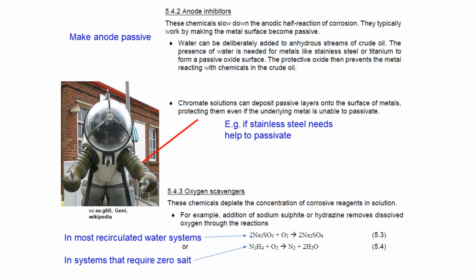We might deliberately add hydrazine to a recirculated water system, and that will react with dissolved oxygen, forming dissolved nitrogen, which might come out of solution somewhere else, and water. So that hydrazine reaction is something that you might use in a stream where the more chemically harmless sodium sulfite was not acceptable. An example of this is in a coolant loop in a nuclear reactor.